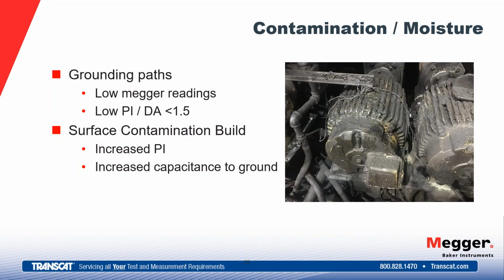Other things that low voltage insulation testing can help us with is to understand the contamination level or moisture level in the motor. Contamination can give us parallel paths to ground, and it would cause lower Megger readings. It may cause a low PI or DA, something less than 1.5. So the contamination provides a parallel path to ground, and we're seeing that affect the low voltage insulation test. It could be surface contamination buildup, as we see on these motors here, a lot of grease and dirt built up on them and the windings also. This increases the capacitance to ground.